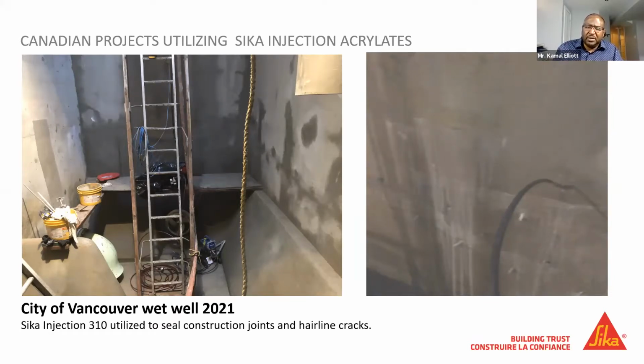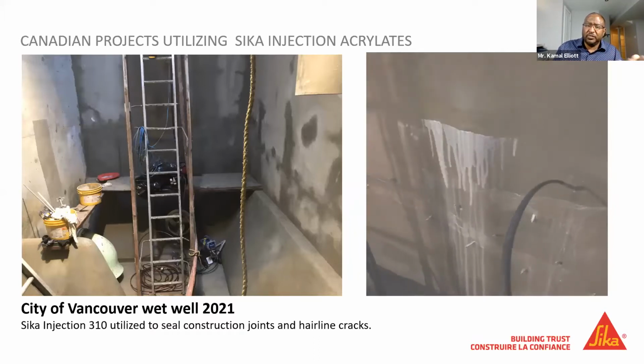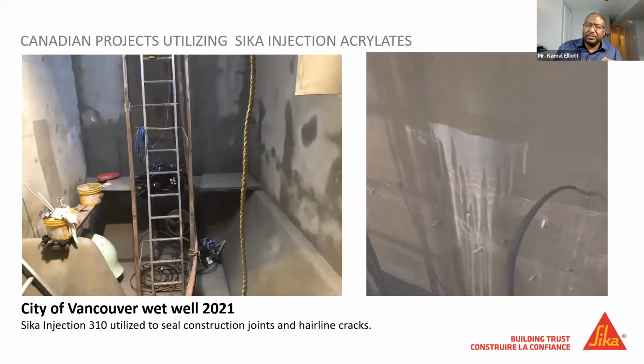The example I show here before I wrap up is a wet well, and they've got some missing or ineffective water stops in the control joints, and also some cracks in the wall. You're going to see a video showing the pump under pressure working its way. You see two horizontal lines where you've got injection ports set up, and he's injecting into the higher one. But you're going to see that the material found its way through the fissures of the wall and then escaped through another crack, which they hadn't prepared for. Now that crack is sealed because this material under pressure can find its way to where water would find its way. There you see the milk coming out of a crack above that is now sealed with the injection gel. So it's another opportunity to deal with challenges on a parking structure down below.